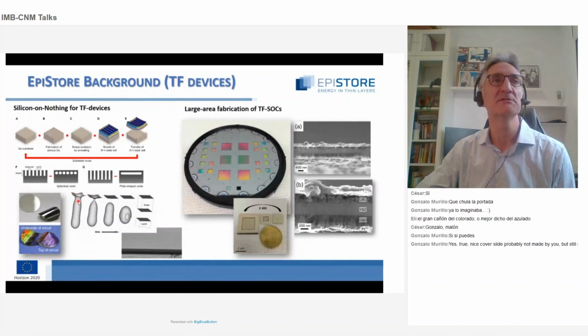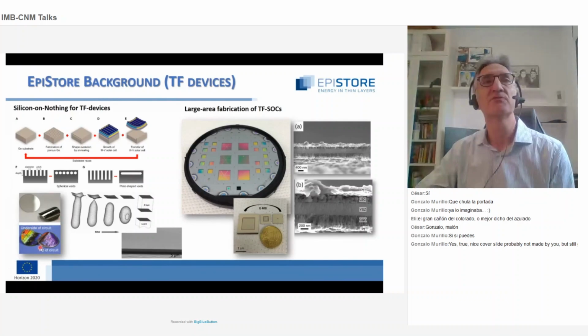The void that is rectangular or cylindrical starts to close, reaching a sphere, okay? And then you are already defining some silicon on top and some silicon at the bottom. And if the pitch is the adequate one, those spheres will coalesce all together, and then they will produce this continuous gap, okay? And as I said, the interesting point is that you can process this upper part, and then you can detach it and transfer it to another substrate.